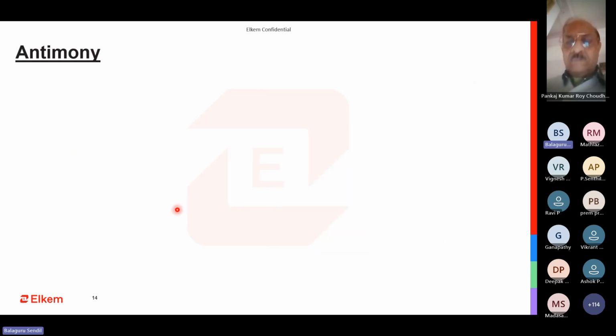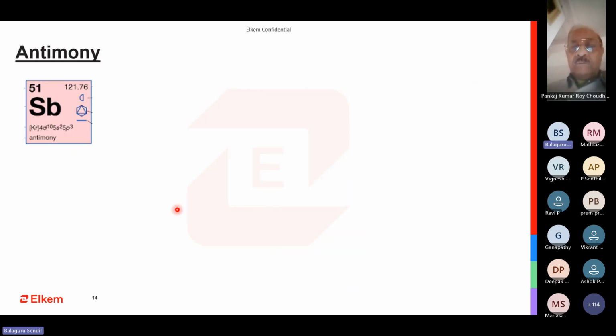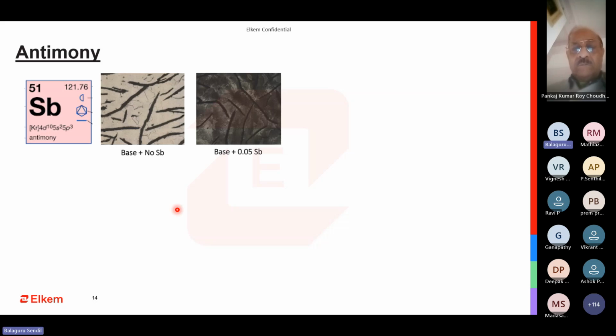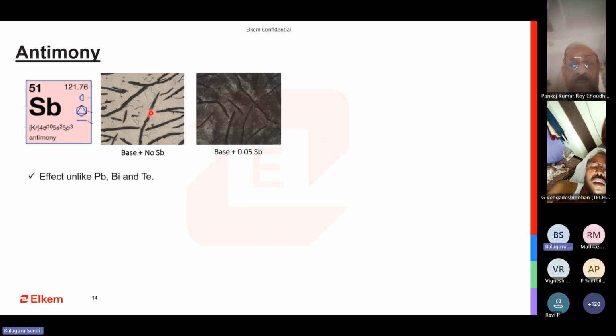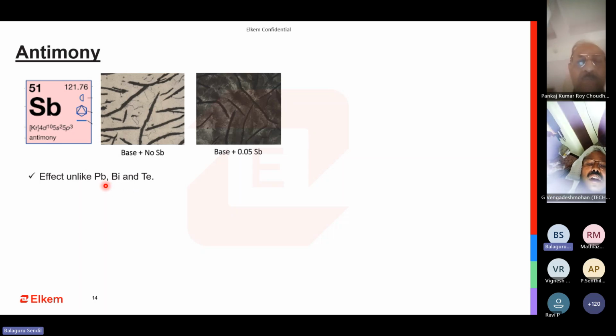The next is antimony. So antimony is Sb. Antimony, I can say that it does only one thing very good. You can see here the base metal with no antimony, and then you have base metal with 0.05 antimony. In case of gray iron, it doesn't spoil the shape and size of the flake. It doesn't cause carbides. This effect is not like bismuth, tellurium or lead. This effect is very clear. It promotes and stabilizes pearlite.